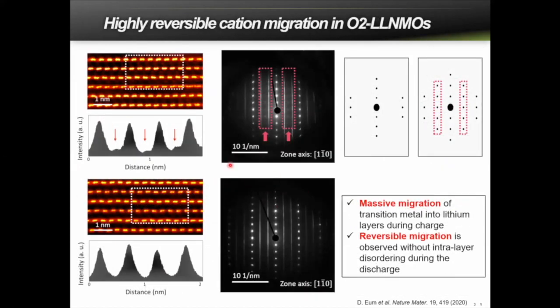We found that this stability in the voltage and the energy density is attributable to the reversible and symmetric transition metal migration during charge and discharge. As we can see here, after charging, the transition metals are visible in the lithium layer, but they disappear completely upon discharge, indicating the reversible migration of the transition metal back to its original position when the lithium is coming back.